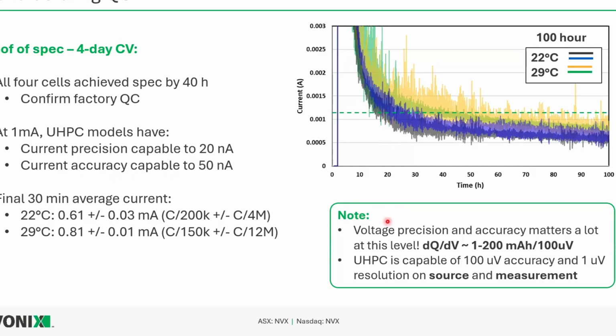A note here is that when we think about doing a voltage hold, even though these currents don't look super small, based on the size of this cell, remember it's 120 amp hours, this is C over 100,000. The dQ/dV of this cell at these voltages is anywhere from 1 to 200 milliamp hours per 100 microvolts.